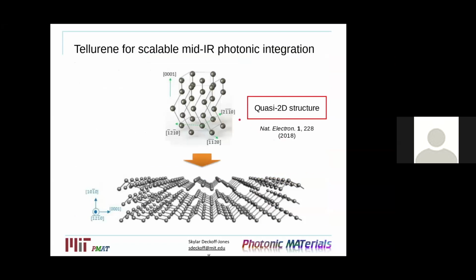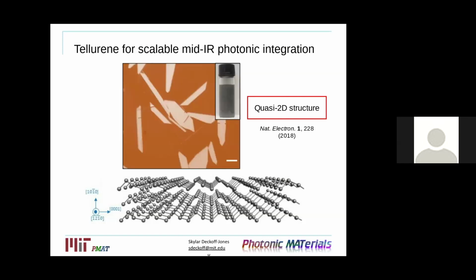It's interesting because it's not actually a 2-dimensional material. Normally the 2-dimensional materials are covalently bonded in one plane and then separated by van der Waals forces along a C axis or a C direction. However, for the tellurene, it's actually these 1D covalently bonded chains of tellurium. However, our collaborators at Purdue have recently developed a solution processing way of creating essentially 2D sheets of the tellurene. So they're able to produce flakes, which are sort of trapezoidal in shape, of the tellurene that have micron dimensions. The scale bar is, I think, 10 microns. So you see micron lateral dimensions.